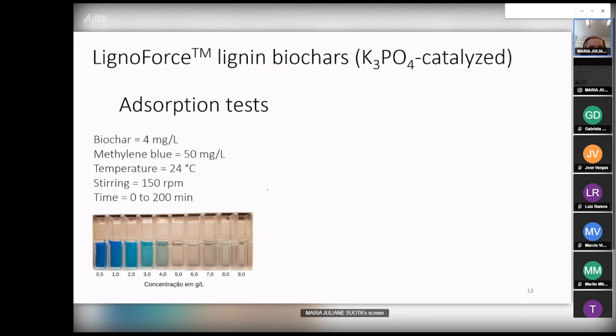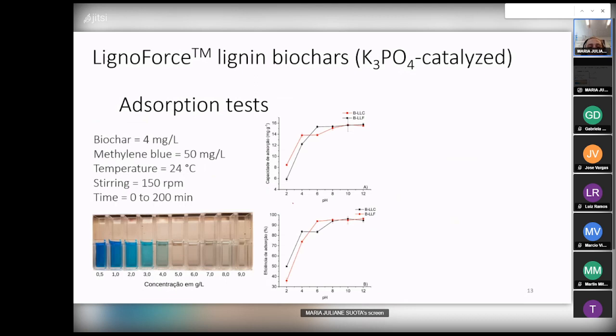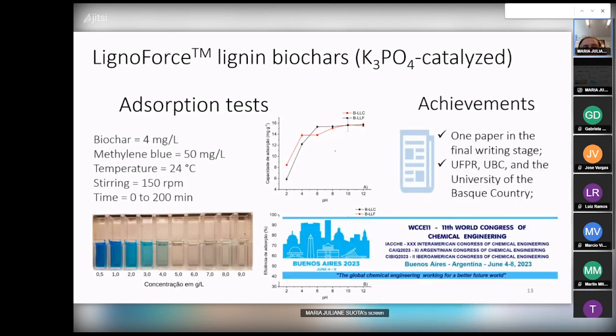which is a very promising result considering the environmental aspects. Later, we analyzed the adsorption efficiency, which was close to 100%, and the adsorption capacity was close to 15 milligrams per gram of biochar, which is very consistent with the literature, considering this biochar was not activated or improved with any process. All these results in the first project generated enough data for producing a paper, which is in the final writing stage.